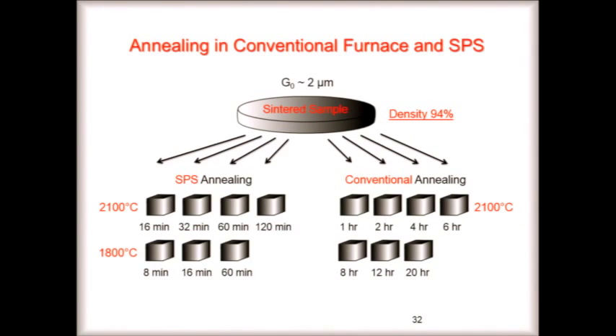There's a problem with SPS in measuring the temperature. Even though they bore a hole and use a pyrometer, the errors can be quite large. We looked at the literature, where some people have done analysis of this, and the worst case was about 300 degrees C. So we did another series of experiments at 1800 in order to compare this.